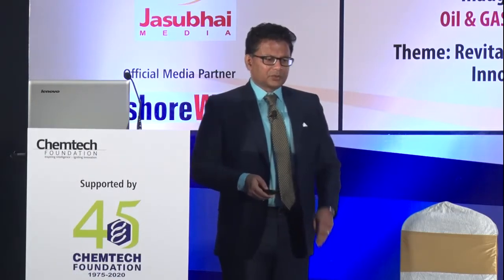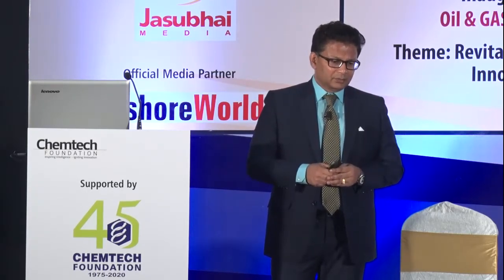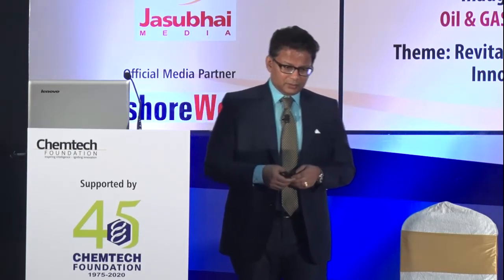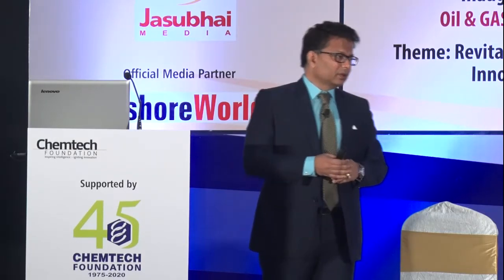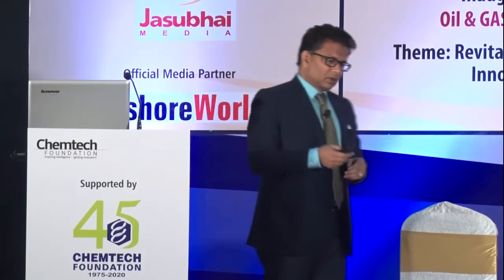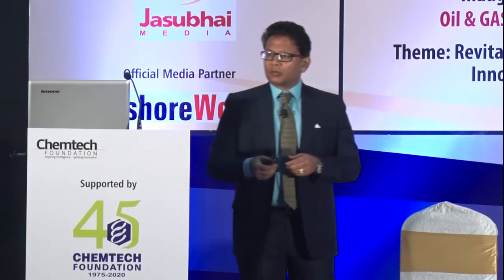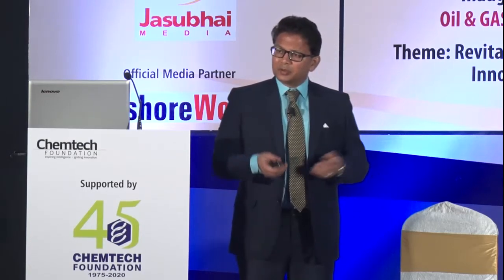Just as an example to tell you that this coating works with almost any media, I show you here one with hydrochloric acid, which is a 10% hydrochloric acid. It could be naphthenic acid in your crude unit. It could be sulfuric acid, as I show, both liquid and vapor. And these coatings remain intact. So these coatings now are being tested for ionic liquid alkylation, successfully approved by UOP in the US.